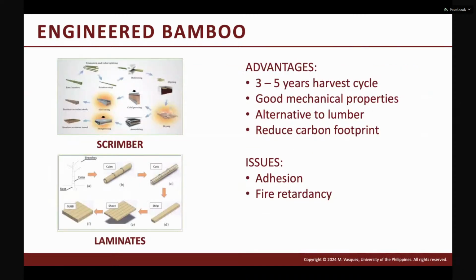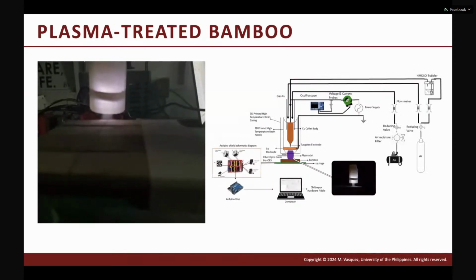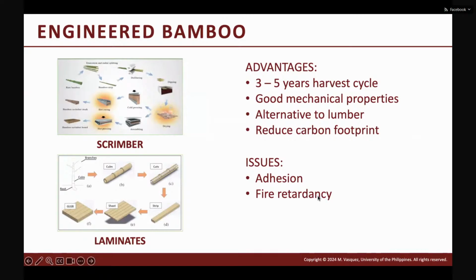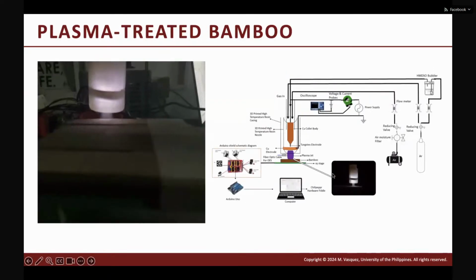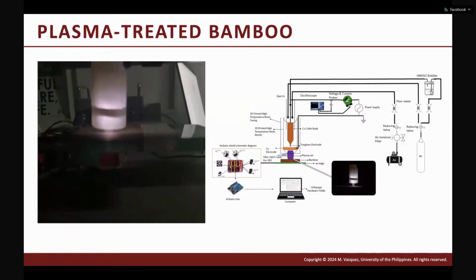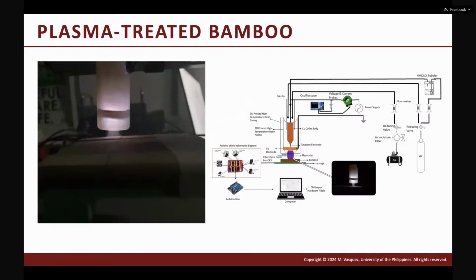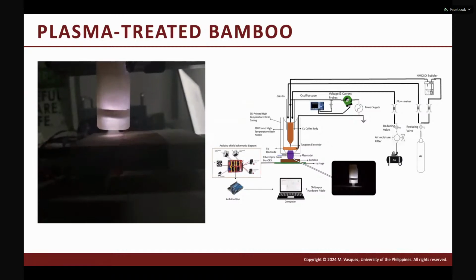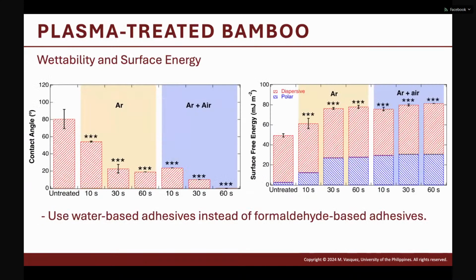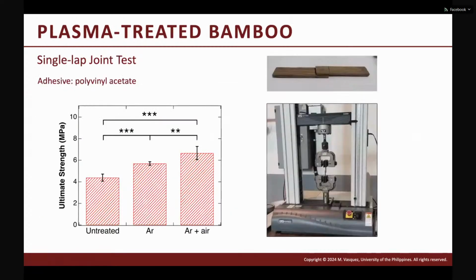So we want to create laminates instead of scrimber, because scrimber has a lot of steps. For laminates, we want to create layers of bamboo. The problem is adhesion of bamboo and fire retardancy. So one of my students developed this plasma system, and we want to improve the adhesion of bamboo and also improve its fire retardancy. So first, we modify the bamboo, make it more hydrophilic, like this one, and improve its adhesion strength up to 55%.